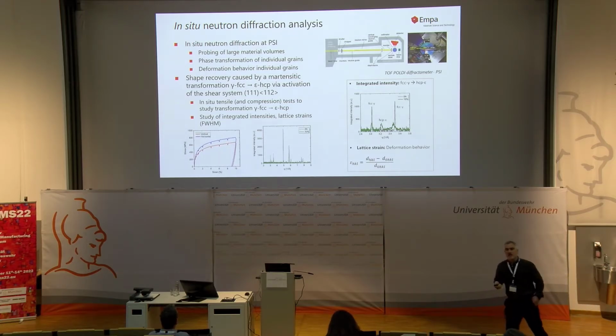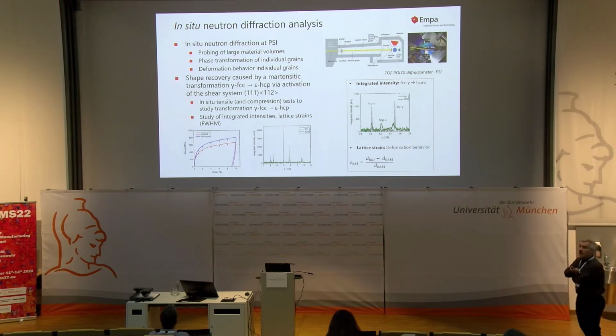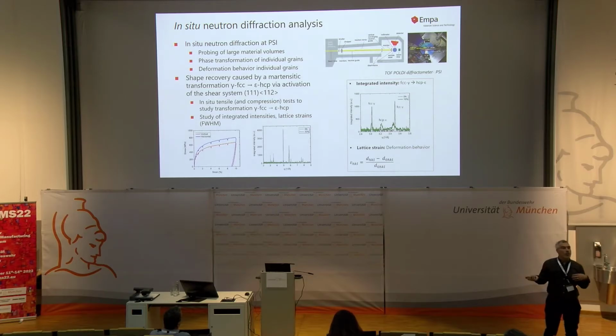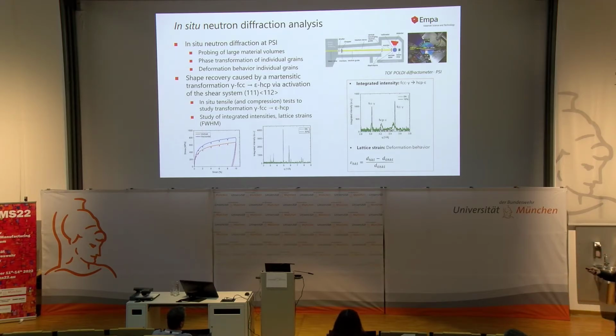It's the texture. So we wanted to get a better understanding of that and went to PSI, in particular to the neutron facility POLDI, and did experiments together with our colleagues there. In situ neutron diffraction allows you to probe large material volumes, and we can look into the phase transformation behavior of individual grain families. Besides, we can learn a bit more about the deformation behavior on a micro scale. And since the shape recovery is caused by this phase transformation, we had a look at the gamma phase and at the epsilon phase.